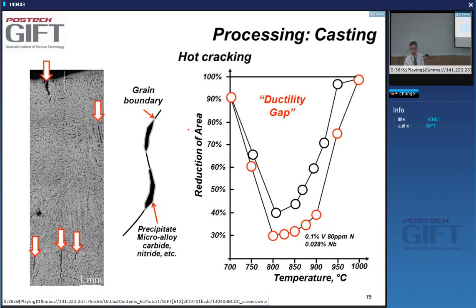If you measure the elongation of a material in conditions of continuous casting, so very slow strains at very high temperatures, and you measure the reduction of section, the plastic deformation where you get the fracture, then if something is very plastic, the reduction before fracture is very large, 100%. At 1,000 degrees, you measure very high ductility. But in the range of 800 to 900 degrees, it just drops to 30%. So your material is embrittled due to these precipitates. And then at lower temperature, the ductility comes back.